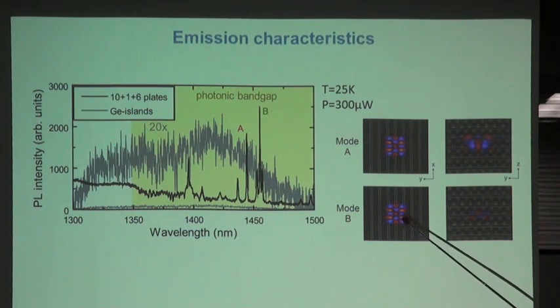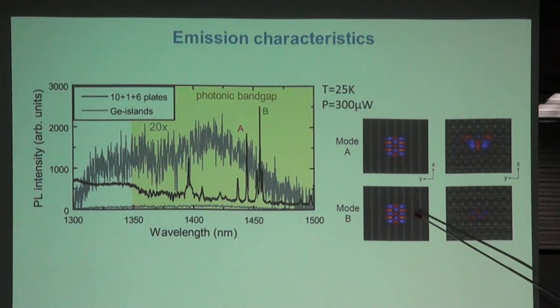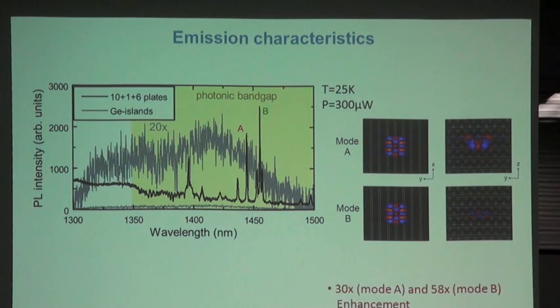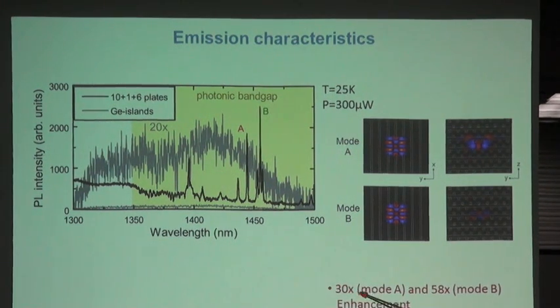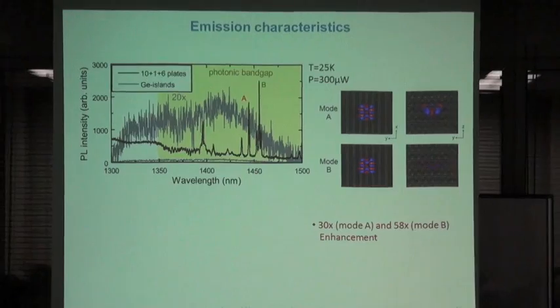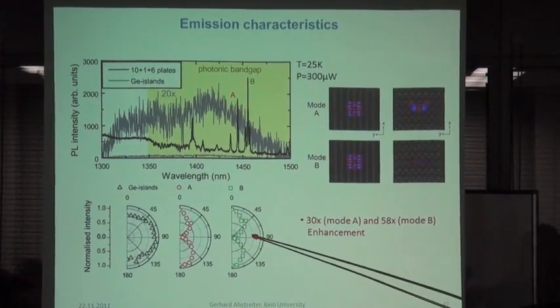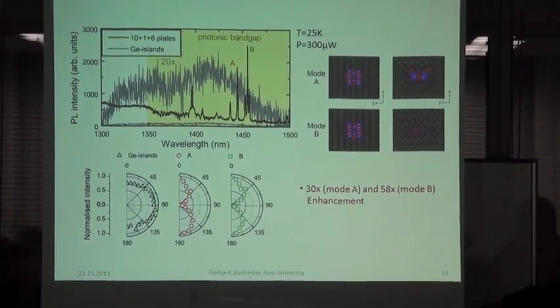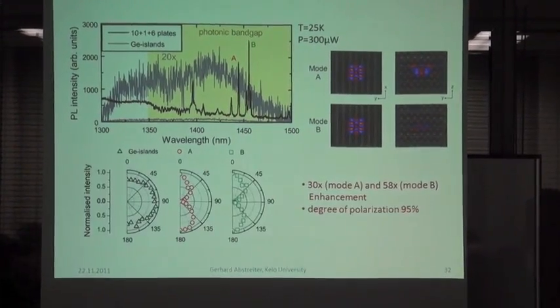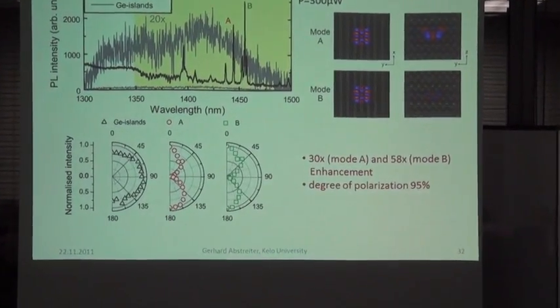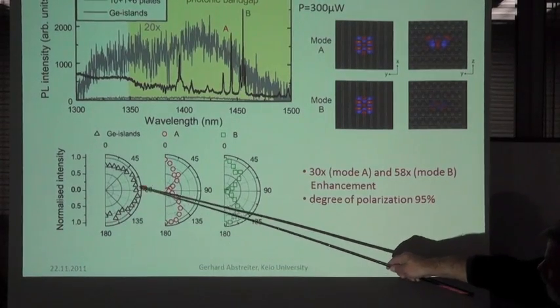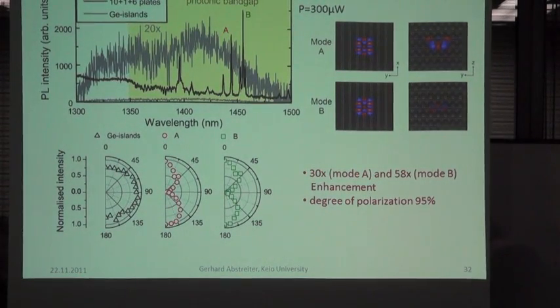And actually, we believe that the 2 strongest modes are these modes from simulation. They are in the plane the same, but out of the plane they have a different pattern. And this is this mode A and B, which is strongest in this photonic crystal. So we have here a factor of 30 and 58 enhancement compared to the unpatterned, and these 2 modes are very strongly polarized here. And actually the polarization is 95%, while this random luminescence is not polarized, so as reference.